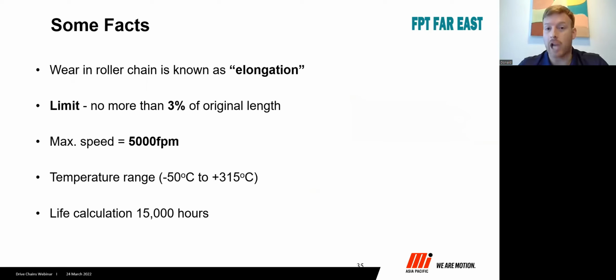Some facts about chain. They do elongate. Chain does not stretch. If you have stretch, it means the chain has gone above its maximum allowable tension. So the chain has actually gone into the plastic region in terms of the material. It's elongated in that sense, but because it's stretched, it shouldn't return back to its original length. So be careful on that. But elongation is common with chains as the chains are operating.